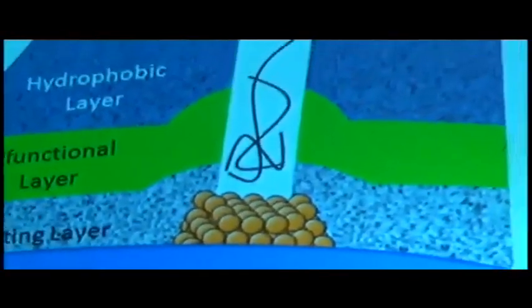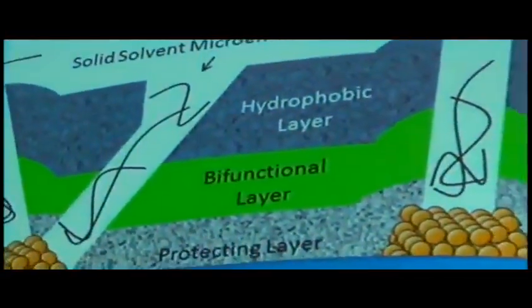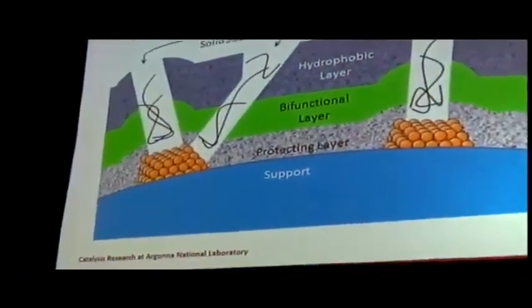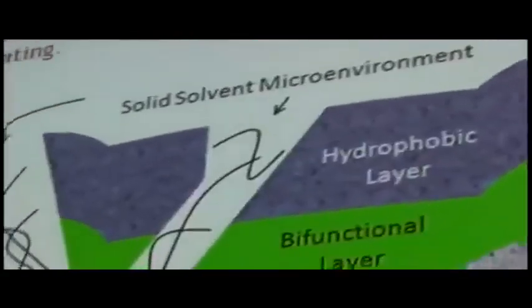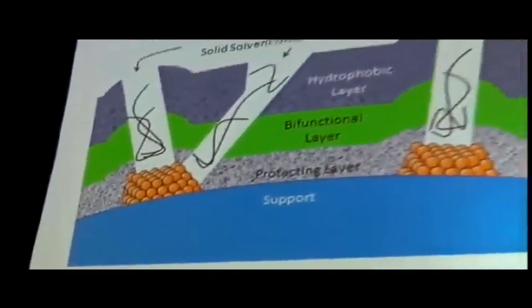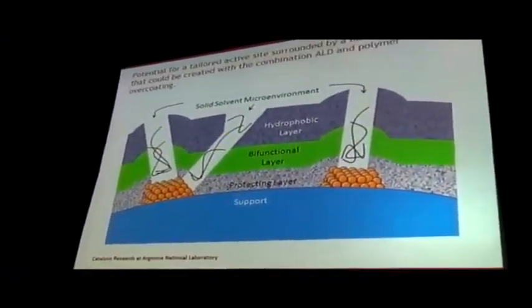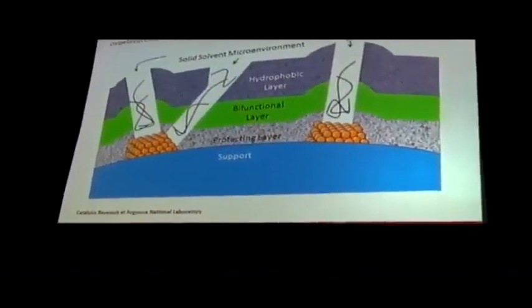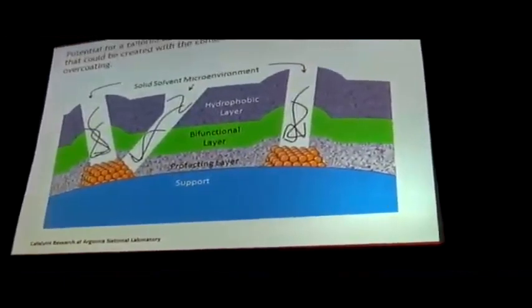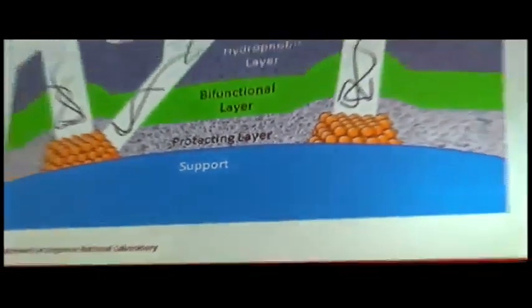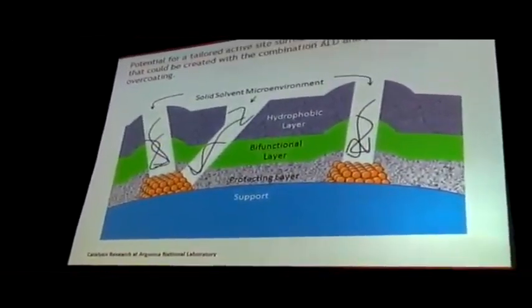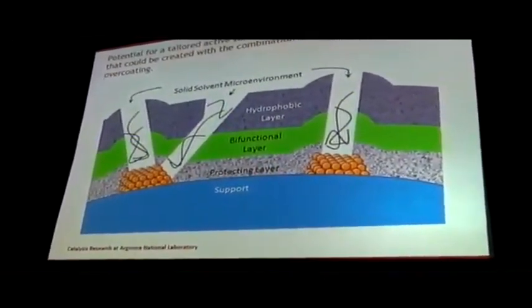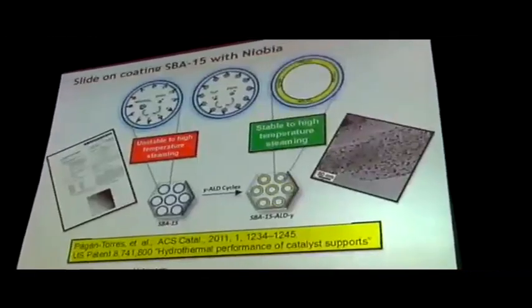Some of the things we're working on right now is tailoring the environment going into and out of the catalyst. This is similar to what people do, for example, with zeolites, changing the nature of the zeolite here. We can put in a bifunctional layer shown by the green there. We can put either a hydrophobic or hydrophilic layer over the top of these by changing the type of ALD overcoatings that we're putting in here, as long as it doesn't mess up the metal. And we can actually add in various types of hydrocarbons into the system to change the diffusion of the material going in there as a function of time on stream.